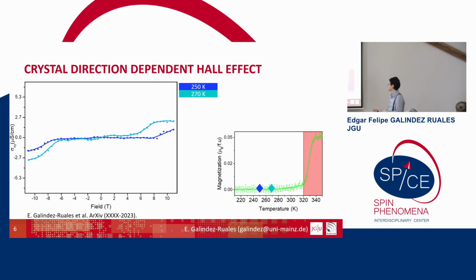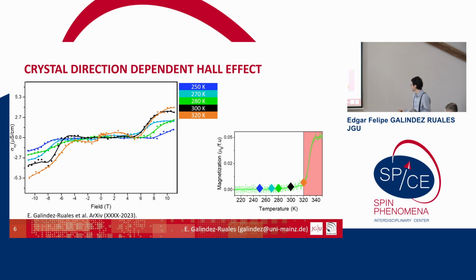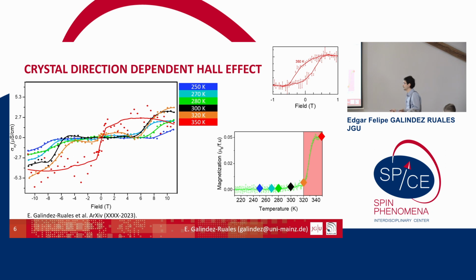But then we increase the temperature, and we increase it more, and the amplitude of the conductivity was varying. That was surprising. And at some point, when we were close to the Morin transition, we started seeing weird stuff. So we went really high, to the easy axis phase, and we have something like this. Measuring this is quite tricky, because to measure the longitudinal resistivity you have to use an electrometer. I will not bore the theoreticians here with experimental details. Basically, you have to measure each device twice, and be sure that it's at the same temperature. That's sometimes a little bit tricky, because you need the same stability and the same conditions.